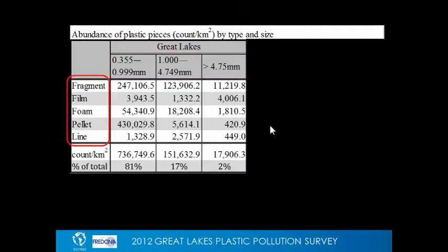In addition to size classifications, we also separate them based upon the plastic type. A plastic fragment would be a hard plastic item that has some fragmentation, some jagged edges to it. A film would be more like a food wrapper, a thin, flimsy type of plastic material. A foam would be like your polystyrene or styrofoam beads, a soft foamed plastic item. A pellet would be those nicely rounded, perfectly spherical, hard plastic items. So the difference between a pellet and a foam is the foam is soft, the pellet is hard. The difference between a pellet and a fragment is that both are hard plastics, but the pellet will be nicely round. And then we have line, which would be like a fishing line, a thin line. This could also include fibers that come off of synthetic clothes when you wash them.